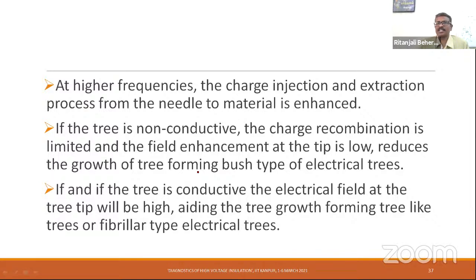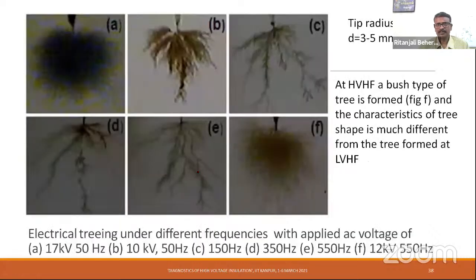At high frequencies, the charge injection extraction process from the needle material is enhanced. If the tree is non-conductive, the charge recombination takes place there, and the field enhancement at the tip will be low. This reduces the growth of a tree, which means forming a bush type electrical tree. However, if the tree is conductive in nature, the tree tips will be acting like the point electrode, and this will actually accelerate the trees, and hence the tree will grow more to be like a fibrillar type of electrical trees. So that is one important observation here.